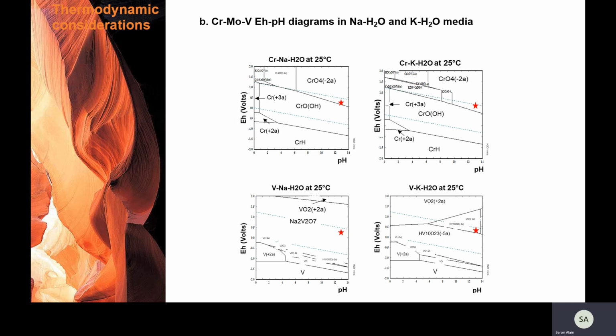The potential-pH diagrams of the systems chromium-sodium-water, vanadium, chromium-potassium-water at 25 degrees C are presented here. The pH and potential values observed during the experiment were measured beforehand. They are respectively around 13 and 0.2 to 0.3 volt in the sodium medium and 13 and 0.3 to 0.4 volt in the potassium medium, and are mentioned by the red star on each diagram.